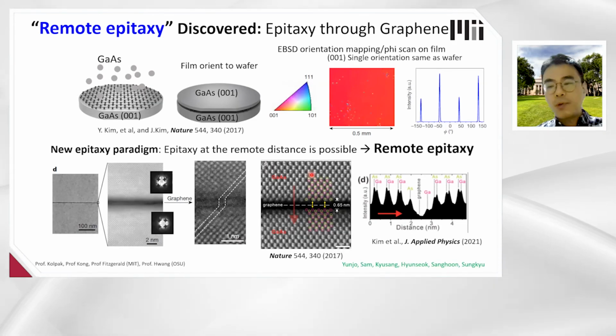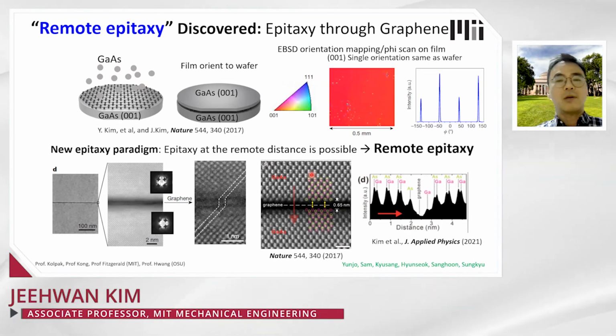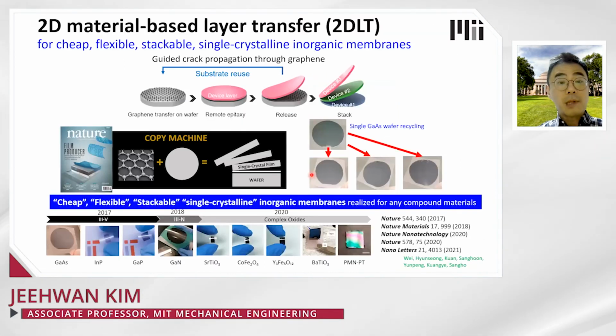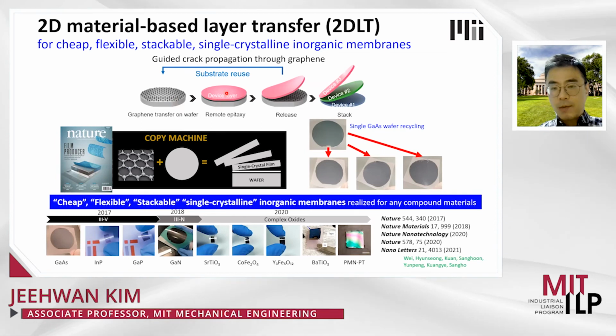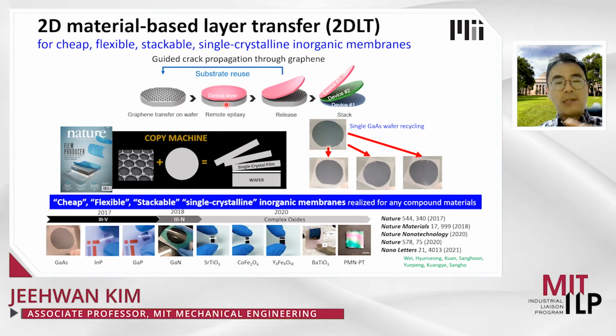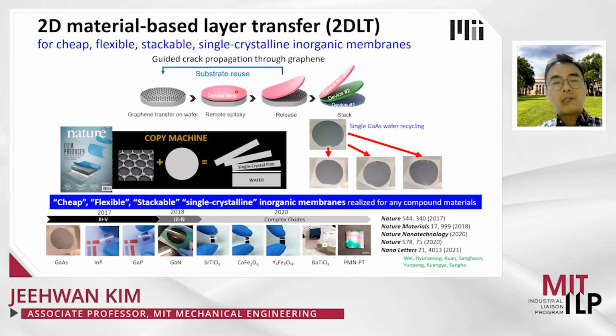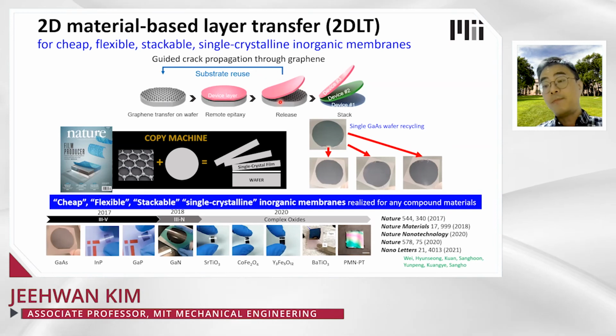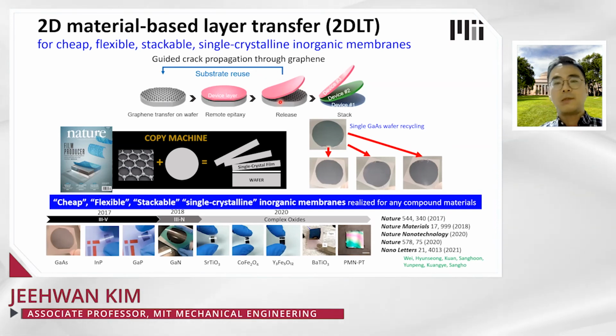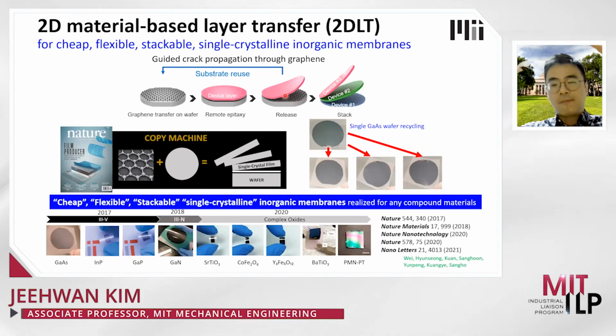Then why bother putting the graphene between the epi layer and the substrate? Here's the reason. Graphene provides a very, very weak interface between the device layer, the epi layer, and the substrate. So once you grow any single crystalline materials on it, you can just peel them off because graphene provides a slippery surface. Then you can do the same thing for different types of materials in different places, and stack them up into one place.